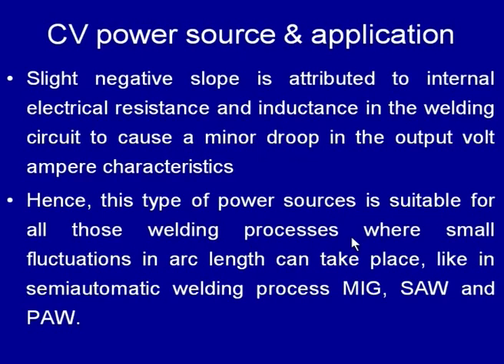Hence, this type of power source characteristic is found suitable for all those welding processes where a small fluctuation in arc length can take place, like in the semi automatic welding process, like metal inert gas welding, submerged arc welding, and plasma arc welding. So, this type of power source is mostly preferred for those welding processes where it is desired to maintain the arc length, and a small fluctuation in arc length causes a great change in the welding current, which is used to regulate the current significantly so that the arc length is maintained. Hence, these power sources are suitable for processes where fluctuation in arc length is not much.